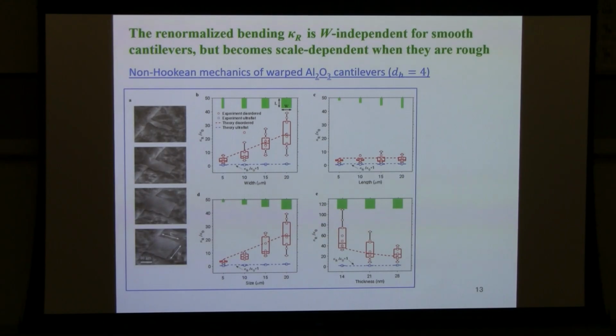And we have a theory of how the strength of this grows with size. And so that's why we need to revisit Hooke's law. We already knew that metallic films in 2 dimensions had a scale dependence, but typically that's logarithmic. This is a much stronger effect. It's basically approximately linear in the size.